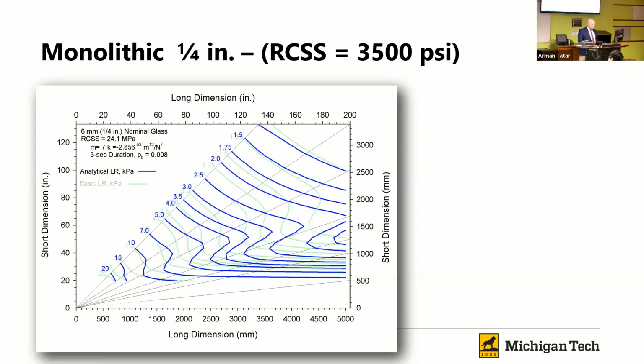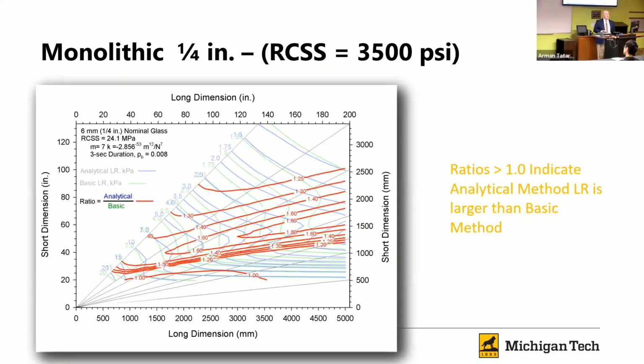So we can divide those two charts and we can come up with these contours, which is the analytical procedure value divided by the basic procedure value. And we find that we had up to a 1.8 times increase when we're out here at these aspect ratios near 3. And we see that that changes depending on where we're at. And we get down to 1 and even a little bit less than 1, but not much, at these very small sizes. Otherwise, just taking advantage of the RCSS and the glass failure prediction model gives us a pretty good boost on the strength of our glass.